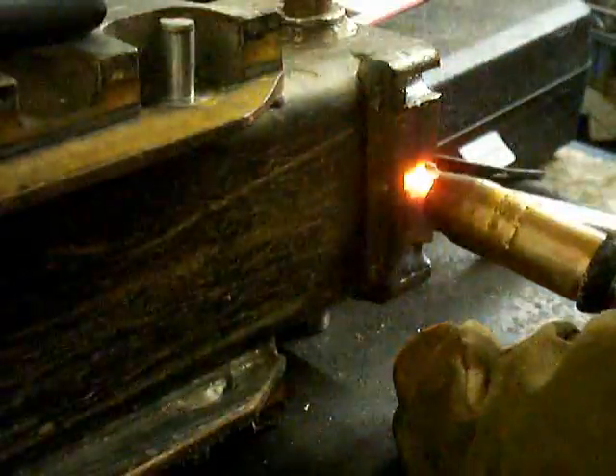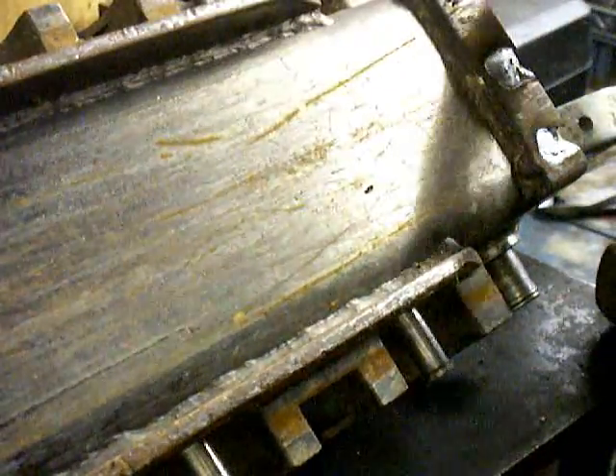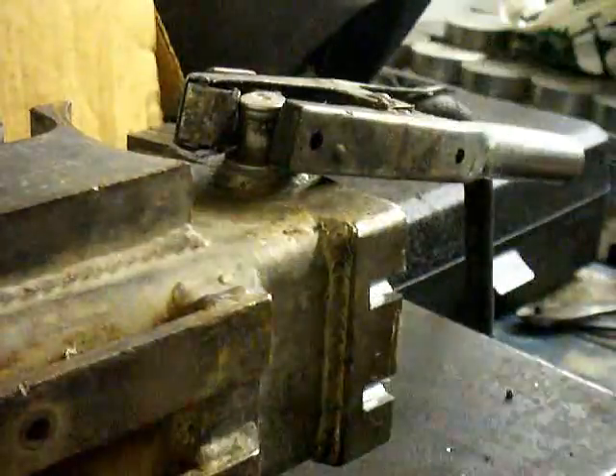I'm pumping a bunch of metal in there and I've got to be careful because there is some crud that seeped into the seams of the metal, and it wants to spooge out when I'm welding. If I'm not careful I'm going to wind up with big pockets of porosity. So I'm trying to weld all the way down into the corner, starting on the corner to get it heated up on the outside, then rolling it into the middle and into the bottom. I've got it sped up here in fast motion — you really can't see much detail, but I want to give you an idea of the sequence. I'm swapping the heat around from hole to hole so I don't get too hot, because when it gets too hot I can't put a nice small tight bead on the corner for contouring.